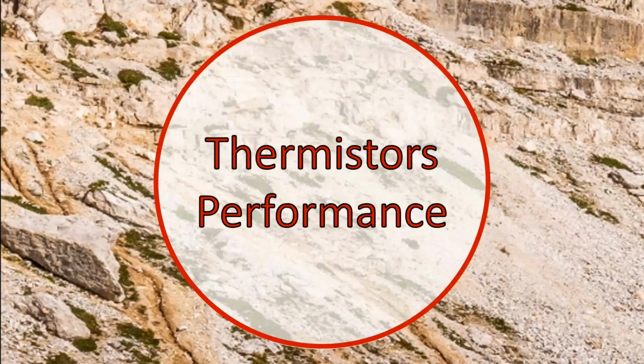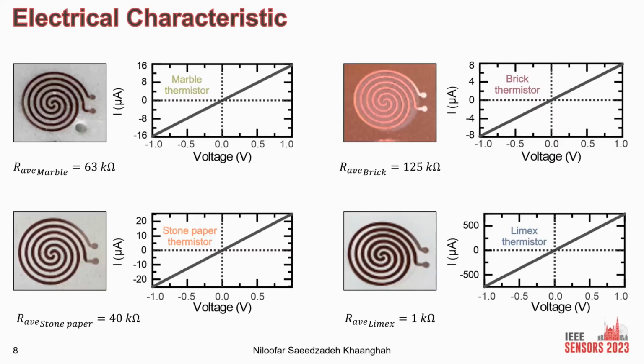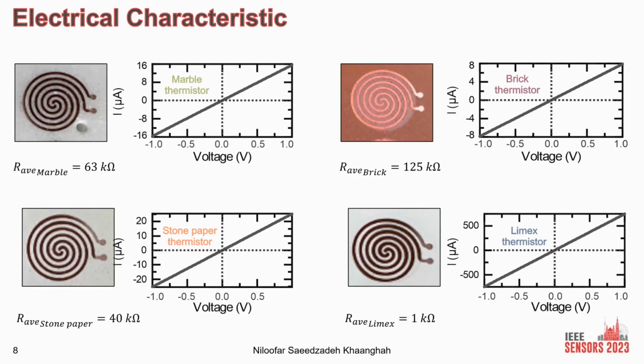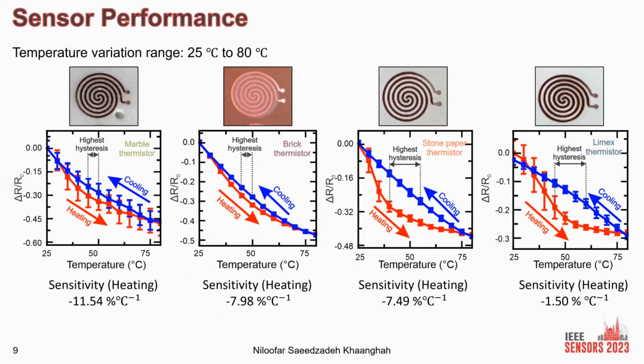So talking about the performance, we took a similar circular pattern of the sensor. Here, the diameter of the sensor is 13.2 millimeter. We started with a current-voltage characteristic to confirm that there is a nice ohmic contact between the copper and the indium gallium zinc oxide semiconductor, and also to confirm that they are conductive. Here you see the sensor performance. The plot shows the resistance variation versus the temperature. The temperature variation range is between 25 and 80 degrees. As you see, when we heat up the thermistor, the resistance goes down, and this is what we expect from a thermistor. We did 5 different measurements. That's where the error bars come from.